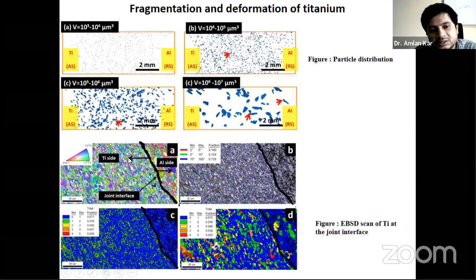And when we look at the microstructure at the interface, this is the interface, this is the aluminum side, and this is the titanium side. We have also seen that there is recrystallization in the titanium. This is quite an unusual phenomenon in the case of titanium subjected to deformation at temperatures as low as 410 degrees centigrade. At this temperature, we generally do not expect recrystallization to take place.